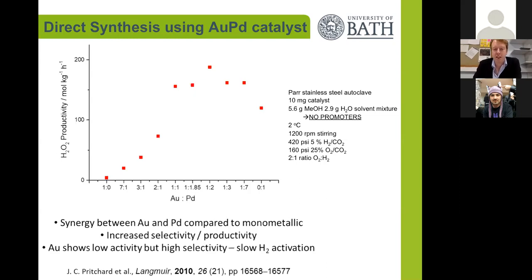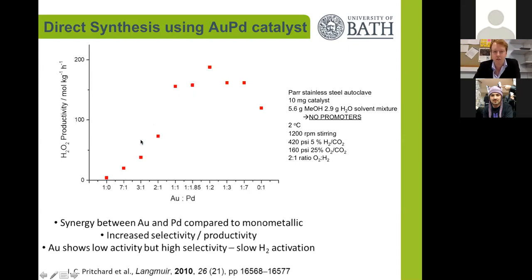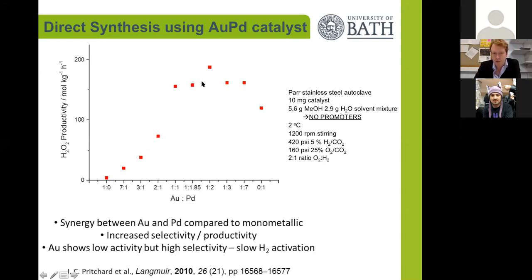Using this set of catalysts, we were able to see the well-studied volcano plot where we see a synergistic effect by adding palladium to gold or gold to palladium. We see a peak activity around 50-50 composition by moles.